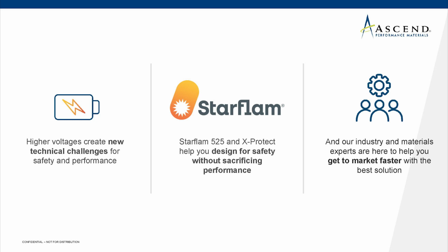So the ductility level that we start off with for those flame retardant materials is slightly lower than for non-flame retardant PA66. And that's the first property that goes down or decreases when you expose it to coolant. But I wouldn't see why you can't use this. Probably not as a drop-in, one-on-one offset against a non-FR version, but with proper design, I'm sure we can make it work.